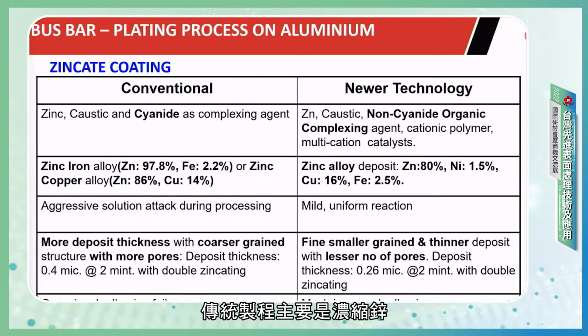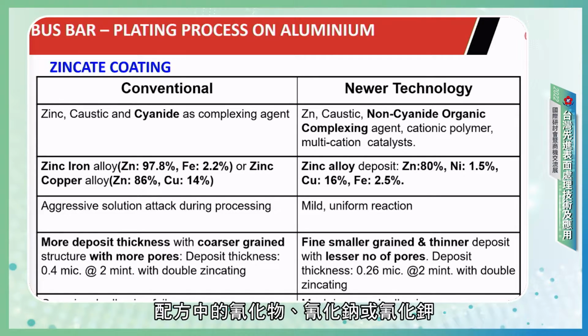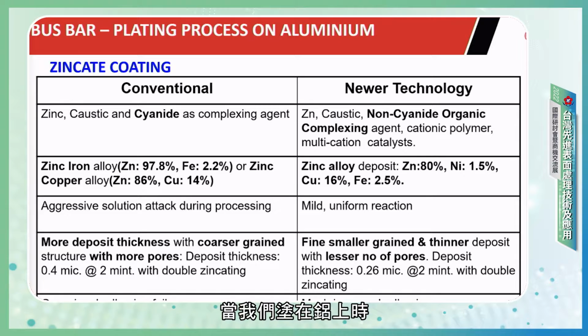So the cyanides are used as stabilizing agents to keep them in complex form. The traditional process mainly contains zinc, caustic soda (NaOH), and sodium or potassium cyanide in the formulation. As a result, when we apply this zincate coating on aluminum, we get a zincate top coat which is either zinc-iron alloy with zinc approximately 97% and iron approximately 2%, or zinc-copper with zinc around 86% and copper around 14%. This is normally the composition of the coating in traditional processes.